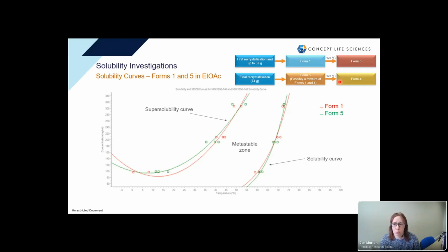This is the first piece of work that we did in the Crystal 16. And we did solubility curves for forms 1 and 5 here. As I mentioned earlier, our original recrystallization process was an antisolvent recrystallization, but I'll come on to that later. For most of our work in the Crystal 16, we worked with a single solvent, just ethyl acetate, and that had been our good solvent in the antisolvent recrystallization.